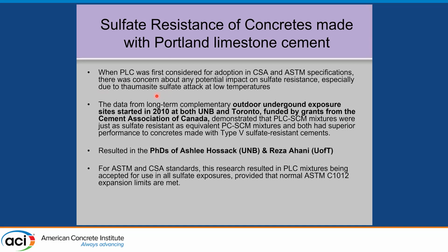I know I cast over 50 mixtures in Toronto, and Mike cast a similar number at UNB, New Brunswick. He supported Ashlee Hossack's PhD, and I supported Reza Ahani's PhD at Toronto. Eventually, based on now 11 years of data, a few years ago we got acceptance in both ASTM and CSA standards for sulfate exposure of PLC mixes, provided that you did the normal C1012 mortar expansion tests. So the concrete backed it up.